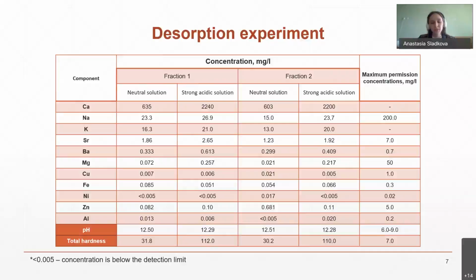To exclude the possibility of contamination of the treated water, a desorption experiment was held. Due to the result of the experiment, the leaching of heavy metal compounds doesn't occur. That makes it possible to apply the material in water treatment processes. But the results also show that the concentration of calcium compounds is high in solutions. That leads to a change in the pH level toward a strongly alkaline solution, as well as an increase in total hardness of solutions.